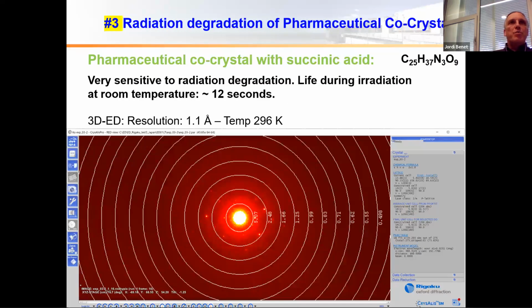So now going to point 3, radiation damage on pharmaceutical co-crystals. We had a system crystallized with succinic acid. We never got the structure by X-rays. We only had very, very small crystals because this was formed by a crystallization reaction. And when we mounted this at room temperature on the 3D-ED system in Tokyo, we saw that the crystals survived only 10 or 12 seconds. After this, they stopped diffracting completely.